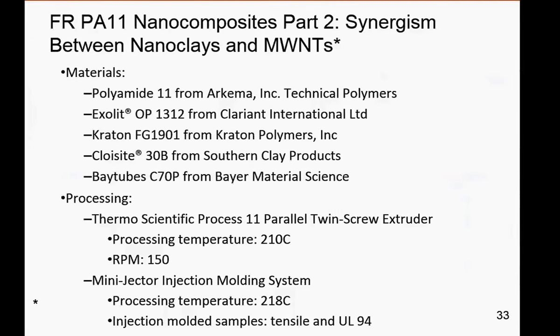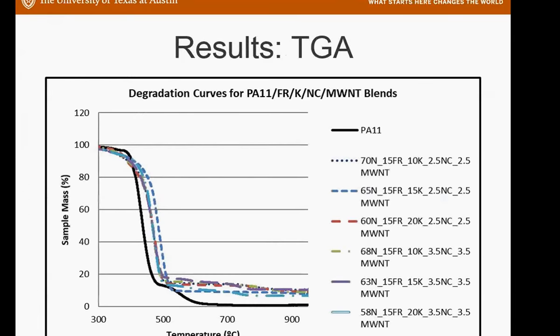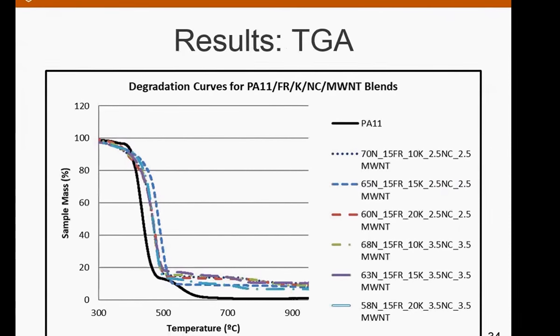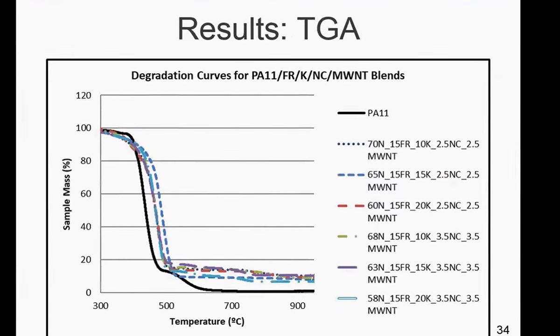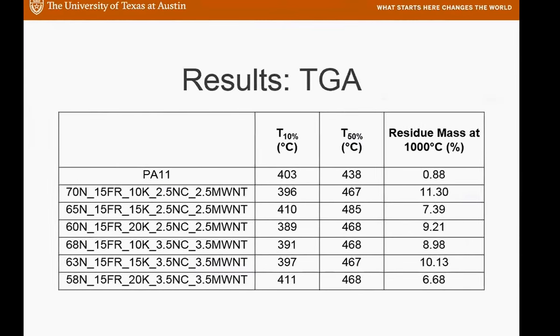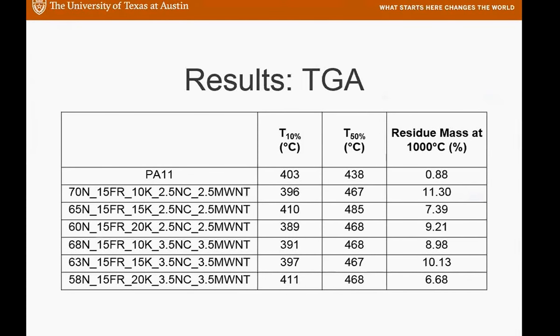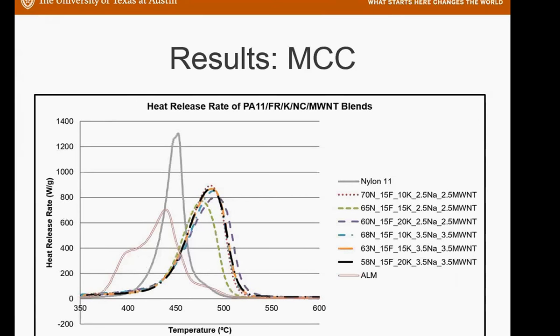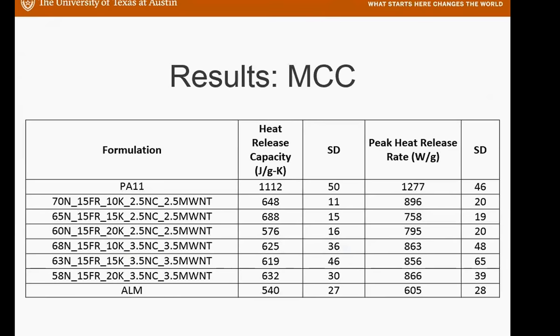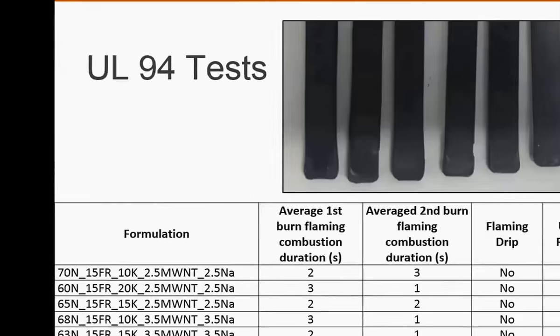There's a lab scale twin screw, and we were able to injection mold these materials and go through the same methodology, TGA, and these are the different formulations we did. Check the TGA, look at the decomposition temperature, look at the char yield, and eventually we also have a device called microscale combustion calorimetry. That we're using for flammability, and you can see nylon is this, the heat release rate, the lower the better, and all these formulations we have, these are multi-wall carbon nanotube, and a combination of clay that we did. But that's what we did, all this down selection.